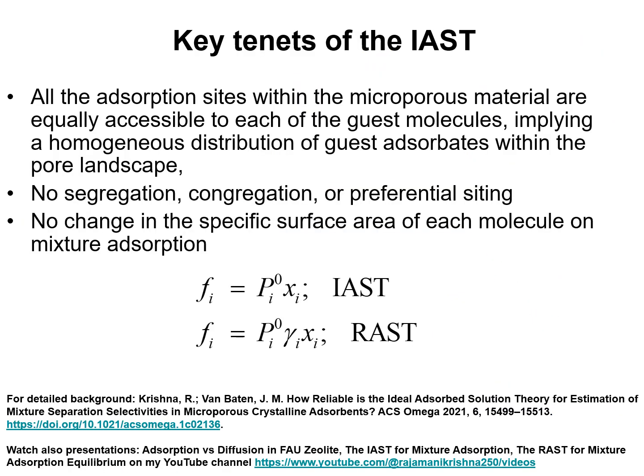The key tenets of the ideal adsorbed solution theory are summarized here. All the adsorption sites within the microporous crystalline material are equally accessible to each of the guest molecules, implying a homogeneous distribution of guest adsorbates within the pore landscape. No segregation, congregation, or preferential siting of any of the guest species in the mixture.